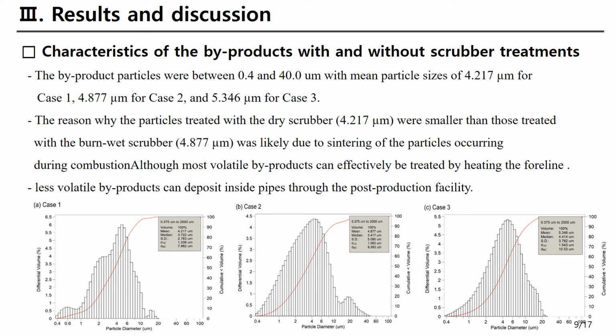The byproduct particles were between 0.4 and 40 micrometer with mean particle size of 4.217 micrometer for case 1, 4.877 micrometer for case 2, and 5.346 micrometer for case 3. The reason why the particles treated with the dry scrubber were smaller than those treated with the burn wet scrubber was likely due to sintering of the particle occurring during combustion.